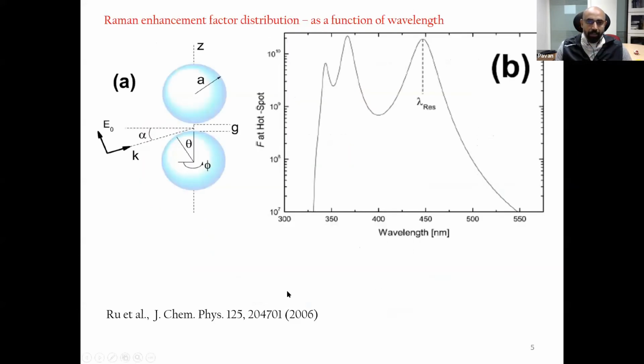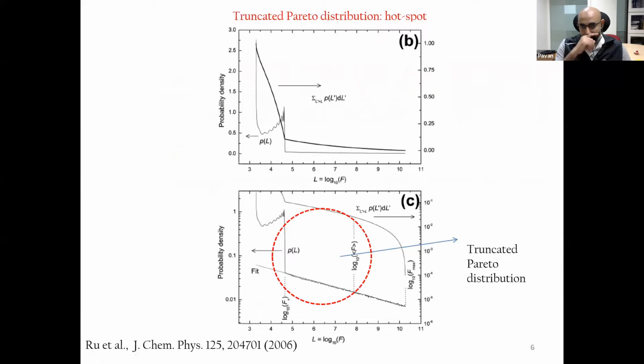Associated with this is also the Raman scattering enhancement factor distribution as a function of wavelength. So for example, if you take an ideal geometry of coupled nanoparticles and you ask how this enhancement factor varies at the hot spot as a function of the wavelength, you can clearly see that it is not uniform across the wavelength. So what it tells you is that there is a specific wavelength at which you can operate, which can give rise to a maximum enhancement factor. Interestingly, a very intriguing aspect of this interaction is that you not only have this wavelength dependence, but you also have the field dependence, which follows some very peculiar statistics.